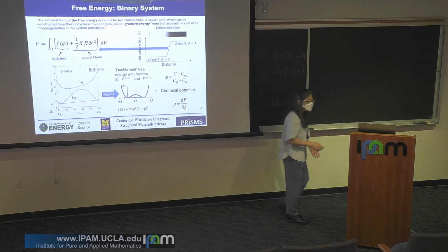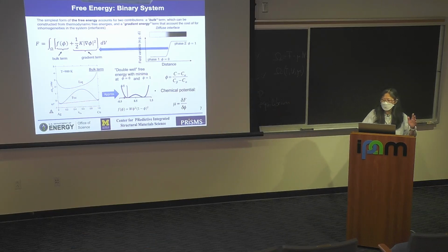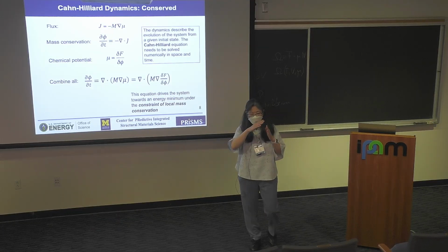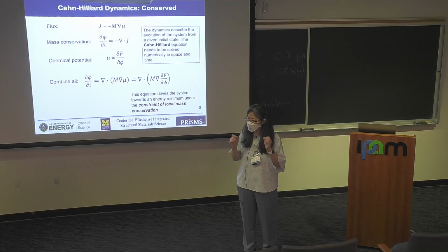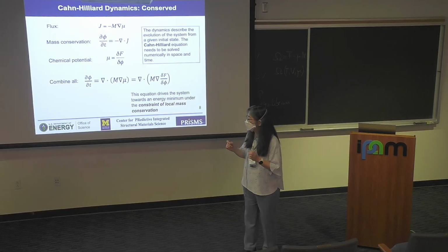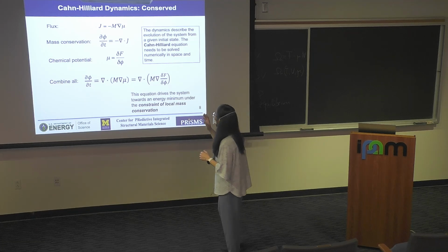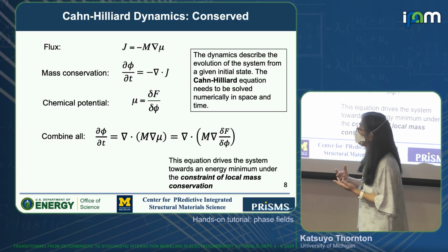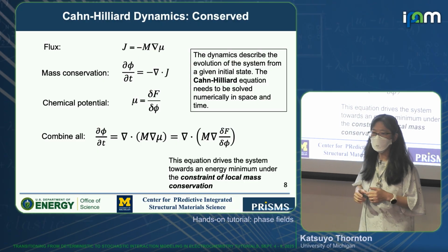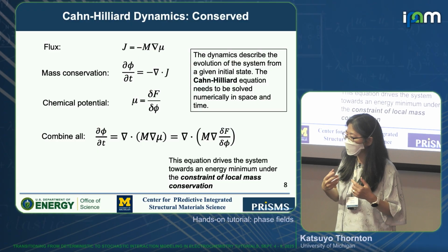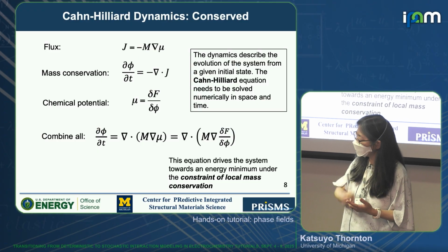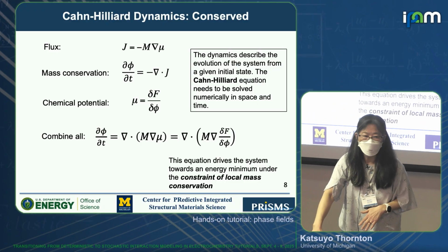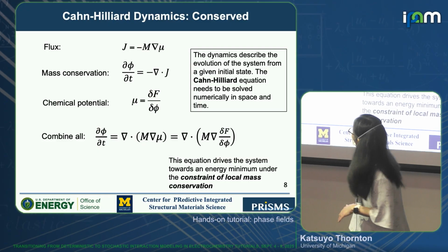Chemical potential has come up so many times, so I think people are already familiar with it. But just to make sure, if there's a change in chemical potential, there's going to be a driving force towards chemical transport. So if there's a gradient that's not 0, then there's going to be a flux. And mobility is going to tell you how easily the species can respond to the driving force. And the negative sign is going to tell you you're going to go down the gradient, right, down the hill.